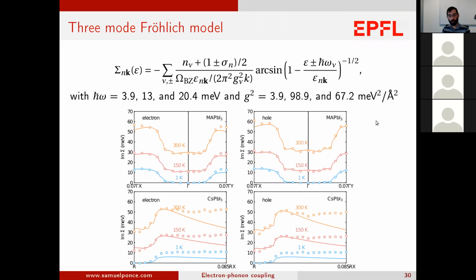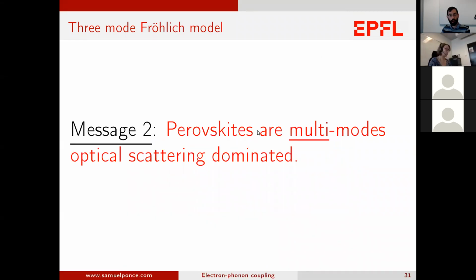The fact that they have a different population makes a difference in the sense that 4 meV is surely much more populated than 20 meV. Yeah, of course it depends on the temperature. Yes, you are fully right, I was not considering that. But what is remarkable is that you can see this relatively simple model, again, we have only 3 parameters. Those 2 are linked. And with that, we can describe this whole temperature range. You see, there is no fitting, we don't put them specifically at gamma or whatever. They really come out from the equation like that. Yeah, which is very nice.